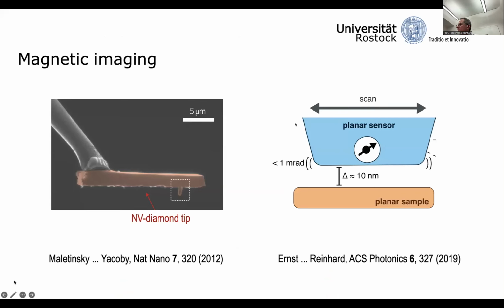And we came up with a drastically simplified scheme, which is based on a somewhat bold idea, which is that it might be possible to also use an NV center in a rather large, tens of microns to millimeter sized planar bulk diamond. And it might be possible to bring this planar diamond nanometers close to a sample of interest if it was possible to align the sensor, the large bulk diamond, with the sample, and if the sample was perfectly flat. Indeed, it might be possible to actually take 2 millimeter large flat surfaces, and you could still squeeze them nanometers close together if you can align them sufficiently well with respect to each other.